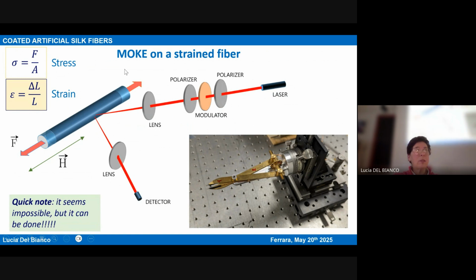And my colleague, Professor Federico Spizzo, is probably the most expert in MOKE in Italy, and also his PhD student, our PhD student, Filippo Lanaro, is on the way. Because they succeeded in doing something even more difficult, namely measuring by MOKE a strained fiber. Which means that the fiber is put between these 2 arms of this device they prepared, and therefore moving the arms, they can apply a stress. The stress is given by this expression, the force divided by the cross-sectional area.